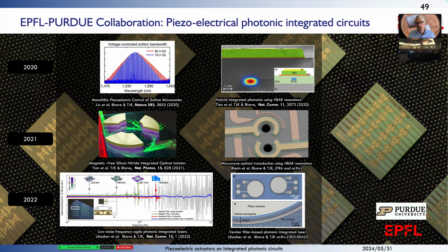With Sunil Bhave's group, we showed we can actuate not only lasers, but also chip-scale frequency combs, which can be useful, for instance, for FMCW LiDAR. You can not only have one actuator, but several ones, create rotating refractive index gratings, which allow you to create so-called circulators, so non-reciprocal devices. You can also use these devices to make microwave to optical converters, whereby you use so-called H-bar modes of the bulk, and use acoustic waves to translate optical microwave frequencies to acoustic frequencies back to optical sidebands. And also, as I mentioned, the frequency agile lasers.